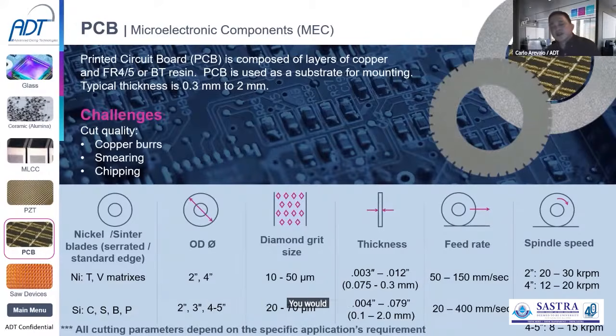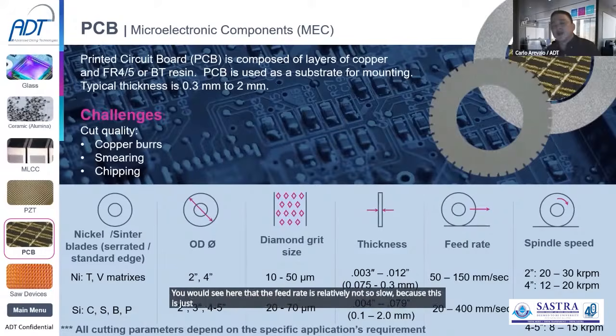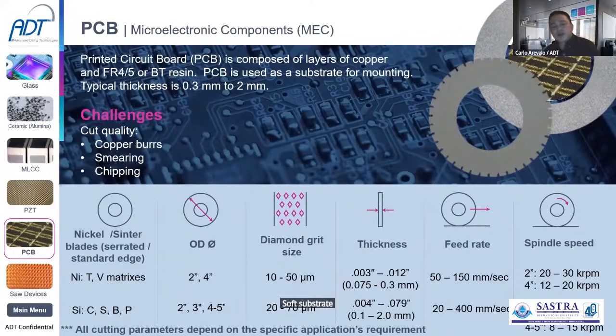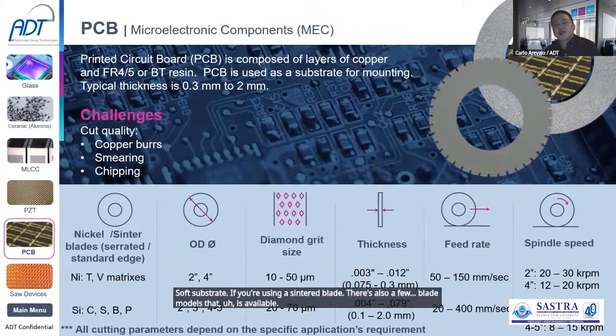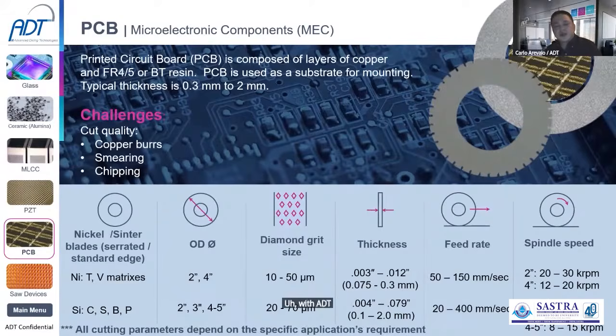You would see here that the feed rate is relatively not so slow because this is a very soft substrate. If you're using a sintered blade, there are also a few blade models available with ADT. They come in almost all blade sizes. The grit size range is 20 to 70 micron. A thickness range of 100 micron to 2 mm is also available, depending on the required kerf or cut line.